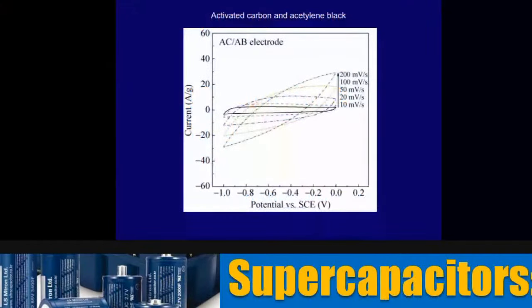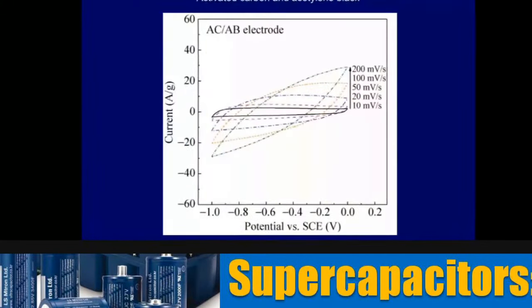So as you can see, the cyclic voltammogram, CV is cyclic voltammogram. What we do is we keep on increasing the applied potential at a linear rate and look at the current that is drawn by the material or current that is supplied to the material. And you can see that the potential is on the horizontal axis and the current on the vertical axis. And you can see that it is mostly linear, indicating that it does not involve any other process but polarization.